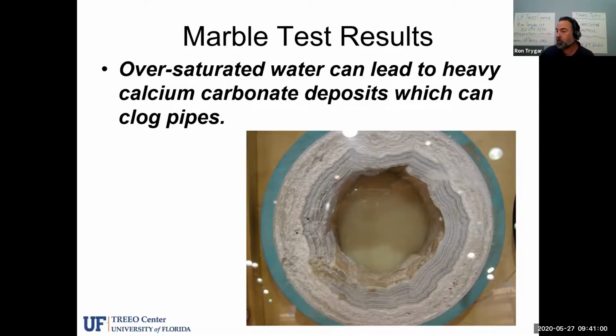So in this picture, you can kind of see the effects of what that would do out in a water distribution system if the oversaturated water was allowed to go out into the distribution system. You can see how much scaling would occur inside a piece of PVC pipe. This looks like C900 water main right here. You can see the wall thickness of the water main, and look at the amount of calcium carbonate deposition on there, and it's in different layers. It almost looks like the rings of a tree, and that piece of 8-inch pipe is down to maybe less than a 4-inch overall inside diameter now because of the heavy scaling that's occurring.